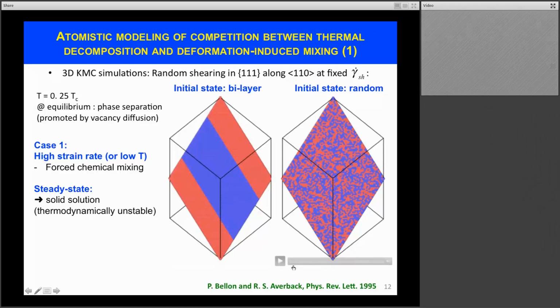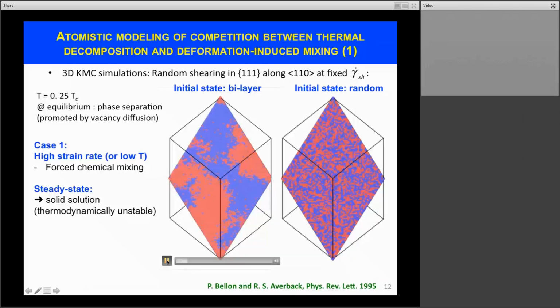And so here we have these pictures representing one 111 plane in this three-dimensional FCC lattice. And here we start with this bilayer state, which is representative of the equilibrium state of the system at this temperature in the absence of plastic deformation. And we're going to observe what happens when we shear this material at low temperature or at a high strain rate. And so now we're starting this short movie, and you see that there are different processes that are taking place,